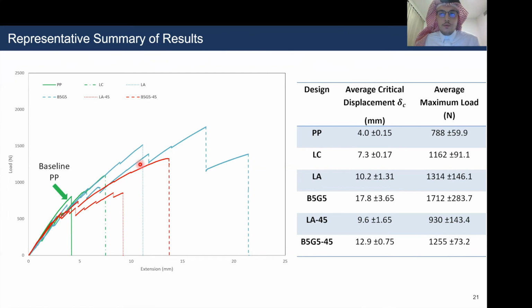So if we were to compare the baseline PP design, which was the weakest, with the B5G5, the strongest or the highest toughness T-joint, we will notice that the load almost doubled. The maximum load almost doubled from 788 to 1,712, more than doubled actually.